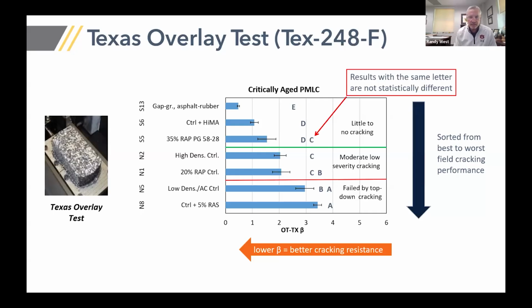These letters A, B, C, D, E are the statistical analyses. Tests with the same letter indicate that they are not statistically different. But we can clearly see that the mixes with an A were grouped together, mixes with C were grouped together, and D and E were the best. So clearly we see statistical differences in the test result. That means really the test can discern good, moderate, and poor performance. That kind of statistical grouping is important.